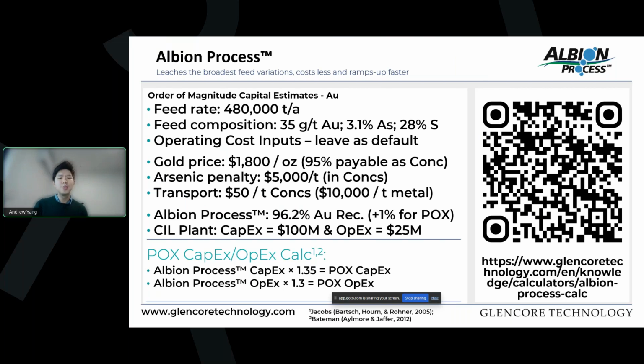For the assumption as well, if we sell it to a smelter, I've assumed that 95% of the value will be payable. The arsenic penalty for the treatment charge, refining charges I've put in there, and I've also assumed some transport costs. For the Albion process, for the recoveries, there are many papers that are published, and some of those papers I've referenced down the bottom, but I've assumed a recovery of 96.2%. For comparison, for POX, we have put a higher recovery of an additional 1%.